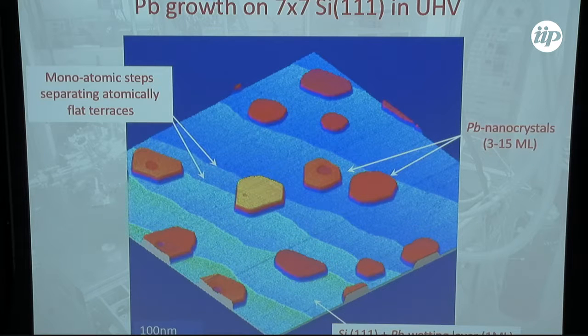This is the system I will speak about. So what you see is the STM image of the system, which consists of atomically flat terraces of silicon, on which we deposit lead at room temperature. And this deposition is as following. What you see coded in blue here is not naked silicon, it is just one atomic monolayer of lead, which is amorphous in this case. It is not superconducting, it is dense amorphous lead. It's metallic but not superconducting.